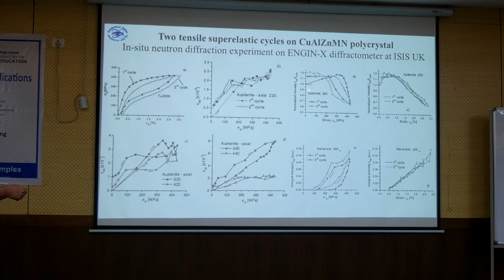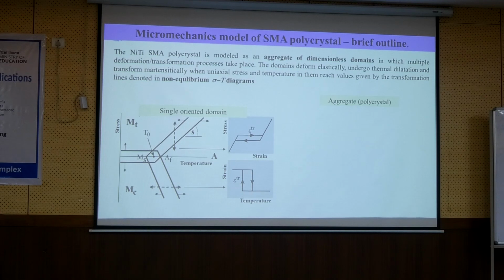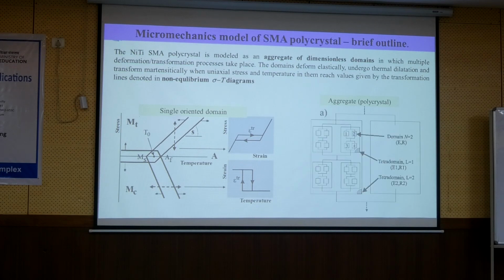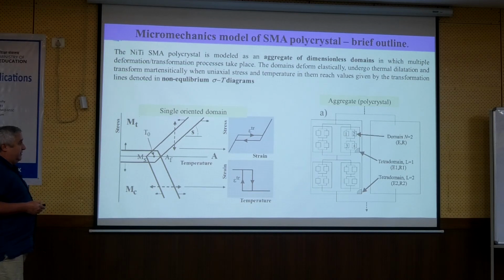Before I spoke about the strain, and in the same way we can look at the integrated intensity, which is here, how it evolves with stress and with strain. So with stress, it's hysteretic. With strain, it's kind of linear in the transformation range. I know it's a little bit difficult to understand. The only way to understand it is to develop some kind of micromechanics models. And we used the knowledge which we had from the single crystal experiment, but without really knowing whether it is the correct way or not.